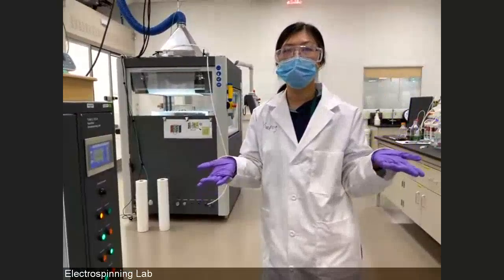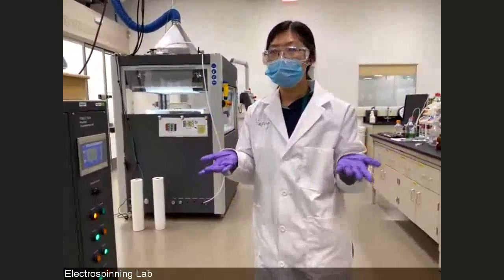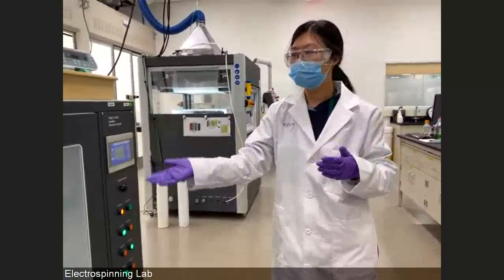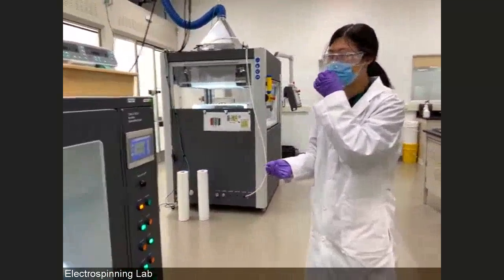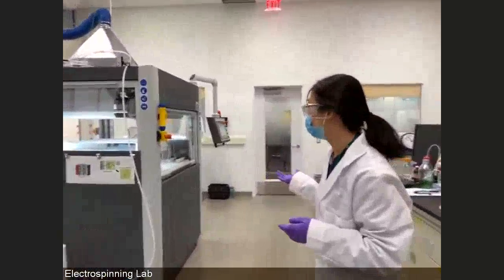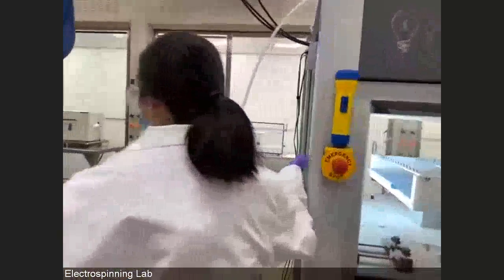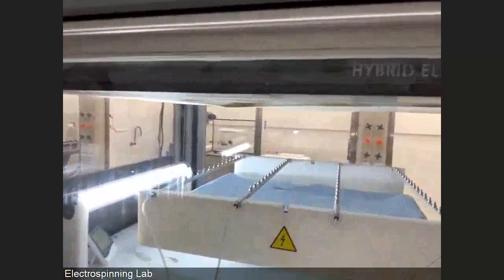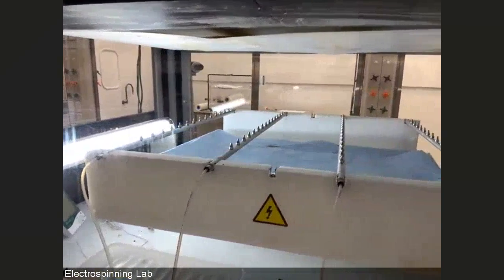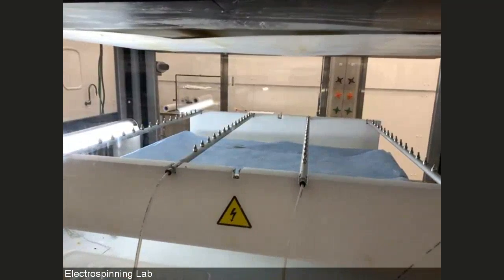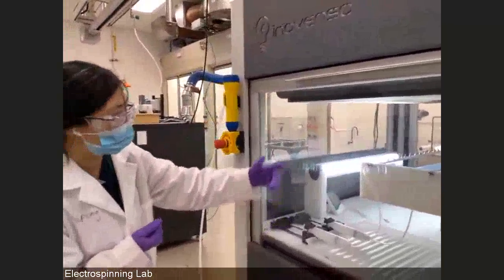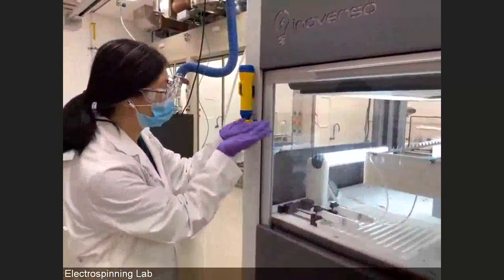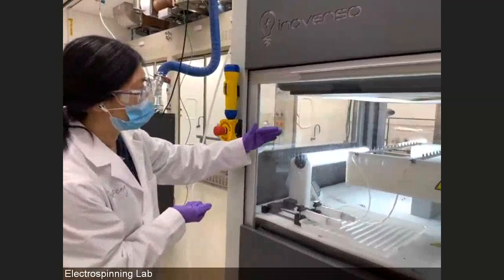Then under the electric field, they generate multiple jets. Another way is to use multiple nozzles, like what we use here. We have 5 nozzles, but we have another setup that has even more nozzles. As you can see, this is our pilot line electrospinning machine, where we have 56 nozzles that are mounted on 4 bars, and each bar is controlled by a separate power supply. In this way we can control the voltage of the nozzles, and we also have the syringe pump that feeds the bar to supply the precursor solution to the nozzles.